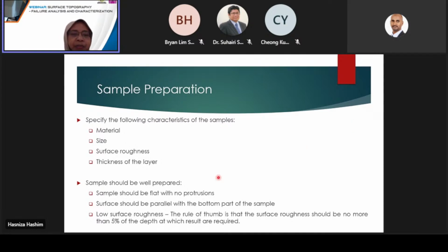The sample for testing should be well prepared. The sample should be flat and should be parallel with the bottom part of the sample. To achieve this, we can prepare the sample with a method like parallel cutting of both the top and bottom surface. After that, we clean with pressurized air or washing in alcohol and an ultrasonic bath, and then do the fine polishing. It's also advisable to inspect the surface of the sample using either an optical microscope, AFM, or in situ imaging, especially for measuring the surface roughness.